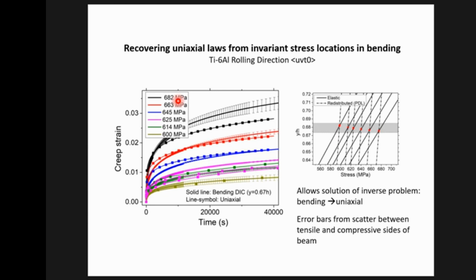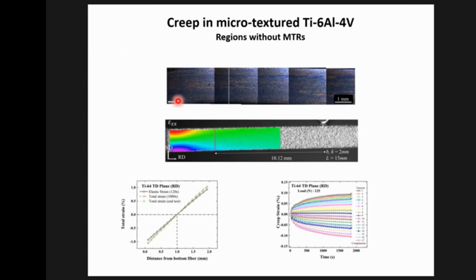So this gave us confidence that one could extend this analysis to non-steady state, decaying creep type of situations, but again, maintaining tension compression symmetry. Now you can do this in polycrystalline titanium. So this is a region which has microtextured regions, but we've taken a particular part for the cantilever which doesn't have any of these so-called MTRs. The top is a polarized light picture, and this was a way of quickly establishing whether you have these textured regions. EBSD is a very laborious thing to carry out on a beam. So again, the strain is linear across the section, and you get these multiple creep curves. And from this, you can establish what your constitutive law is in a polycrystalline Ti-6-4.